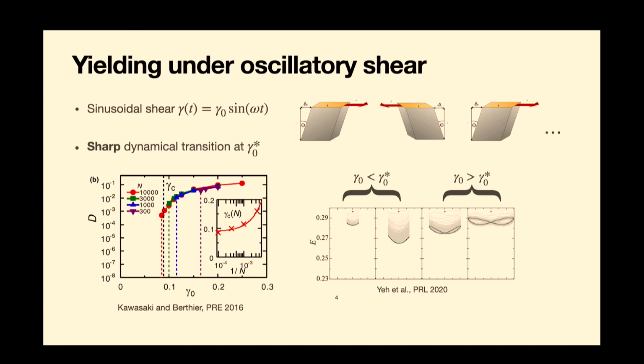Okay? So what you see is that at low strain amplitudes, the energy just goes back and forth, and it's uniquely linked to the state. There's no hysteresis. So that's a system that hasn't yielded, and it's basically just deforming elastically back and forth. The forward cycle is the same as the backward half of the cycle. Okay? Whereas above, you get this sort of hysteretic shape. So on the right here, these right two plots, the point here is a bit, I've got my finger in front of it, that's the problem.